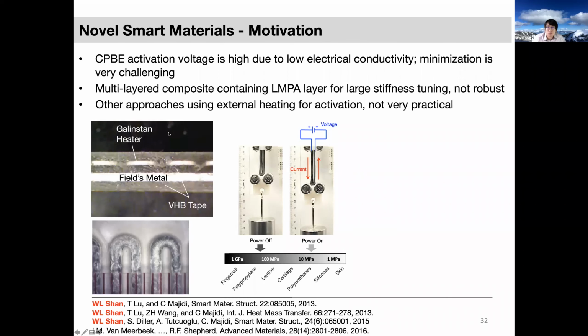We also tried other approaches for these smart materials for stiffness tuning. This is one work done by me at CMU. We were using a multi-layered composite containing an LMPA layer for large stiffness tuning. But this structure turned out to be not robust. As you can tell, this is literally a multi-layer structure, and this is the top view. You can see the soft feeder channel here made of galinstan. The issue with this is robustness. When you stretch it, you can stretch it a lot, but then it's hard for it to go back to the original shape, given the elastomer we're using. This is literally a reservoir of fused metal. Once it melts, it's hard to go back to its original shape because it's very heavy, and this is just a block of the smart material.